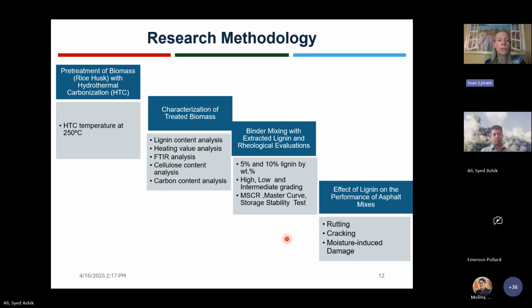We pre-treated it. We chose hydrothermal carbonization, a temperature at 250 degrees C. One thing I want to mention is that at that point, you have the water that's in there with the biomass, and it has more H+ ions and also more H3O+ and OH− ions. And so that makes it a different kind of solvent than standard water. And the reason for that is because this is water at 250 degrees C, which is way above the boiling point, and it's also high pressure. And so that's why you still have liquid water in the process.